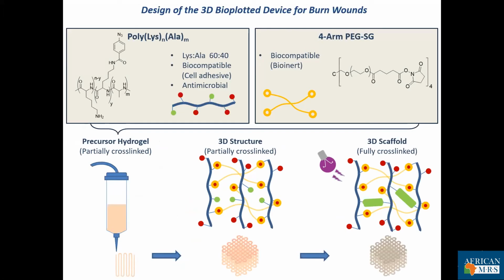So just showing the fabrication approach for your 3D bioplotted device. Firstly, an initial hydrogel was created. This precursor hydrogel was partially cross-linked. So this was the first cross-link between lysine and alanine together with your 4-arm PEG to create the initial hydrogel, which was then 3D bioplotted. And this was then secondly cross-linked to obtain a fully cross-linked scaffold via UV light.